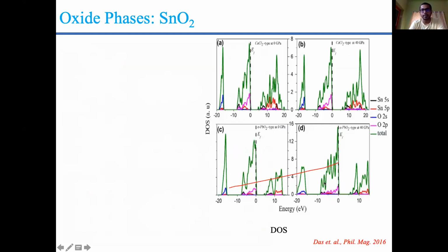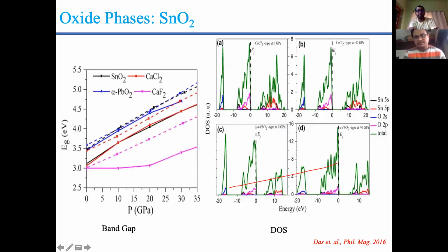And another thing to notice, you can see the band gap increases with pressure. So the band gap evolution of all these phases with pressure is plotted here, and as they have luminescence properties, this increase in band gap makes them industrially very demanding. So these are the conclusions of this work.